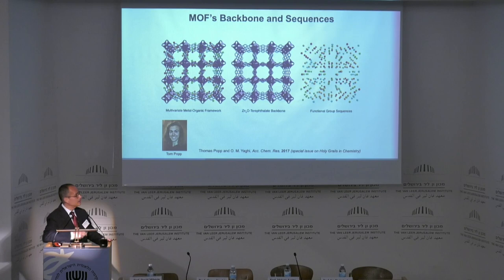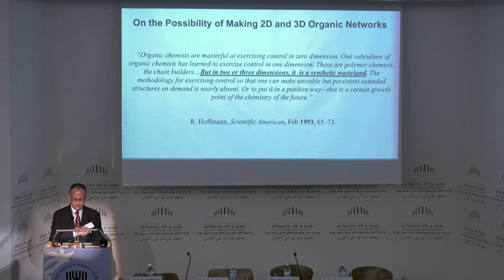Now we know exactly where they are. We know that they are all on the orthophenylene unit. We also know their ratios relative to each other, and we know how far they are from each other. We know a lot because the backbone is periodic. But what we don't know is their spatial arrangement. What is sitting next to what? That's the challenge that we need to figure out. But in the meantime, these structures are trapping carbon dioxide 400% better than structures that are not mixed in this way. So I think that this is a direction made possible by the fact that you have a periodic backbone that can be functionalized. Any other structure that is functionalized in this way would not maintain its structure. So I would say that that's another direction.